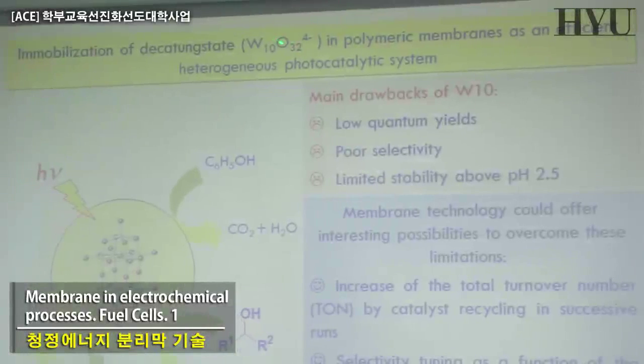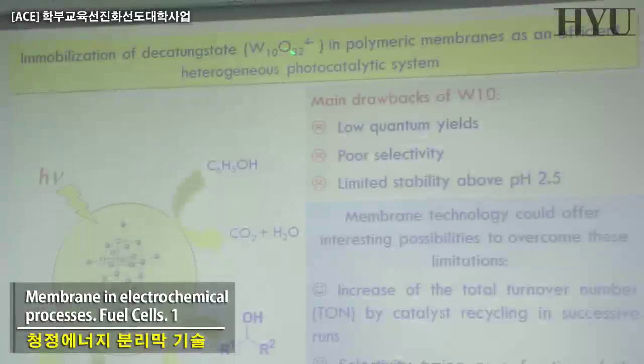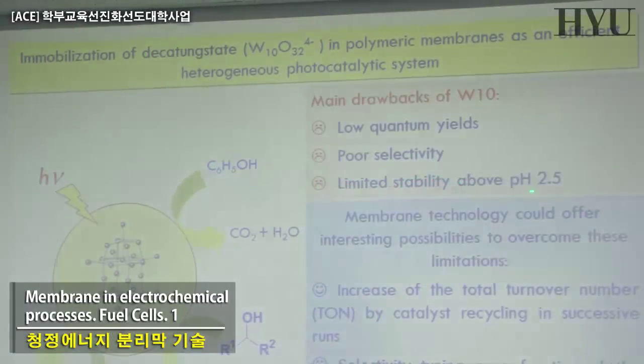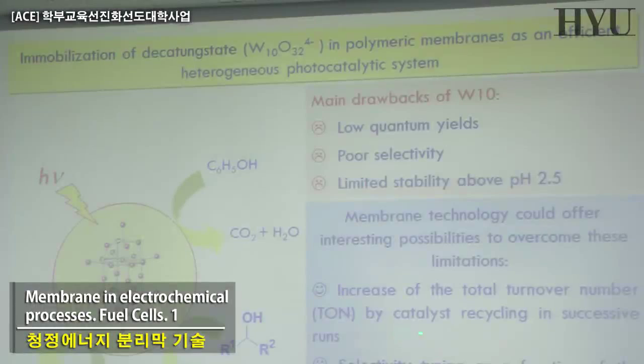This is one of the cases in which we have been working more, this W10O32, a complicated structure normally, and quite interesting for some aspects, but there are different drawbacks, some negative aspects. For example, the low quantum yield, the relatively poor selectivity, and also limited stability above pH 2.5, basically. What is possible to do with membranes in principle is just what we have been discussing already.